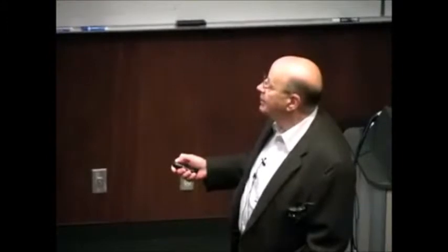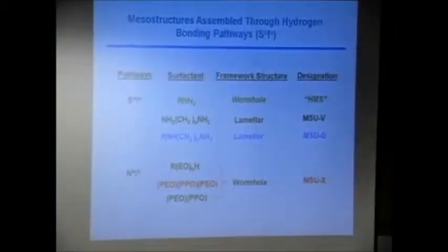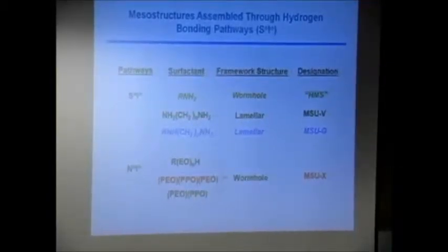So what we had realized is that we could probably make these mesostructures using electrically neutral surfactants, like amines, some of which are shown here, or block copolymers, in which we have polyethylene oxide and polypropylene oxide segments, the ethylene oxide segments being hydrophilic, the propylene oxide segments being hydrophobic. And so these were electrically neutral surfactants that once you have the mesophase form, the heterostructure form, you could anticipate being able to solvent extract the surfactant from the pores and recycle it.